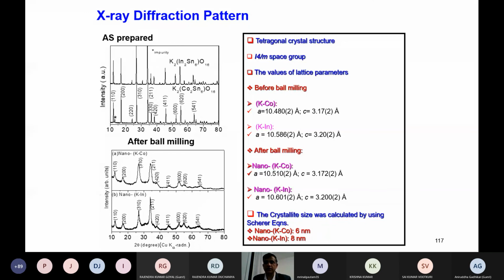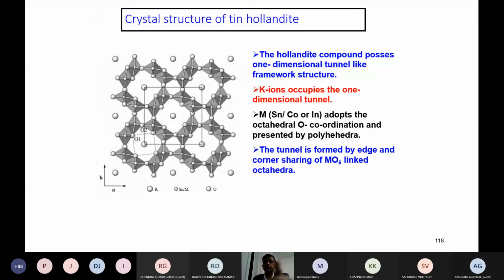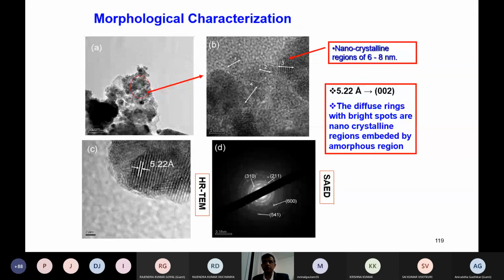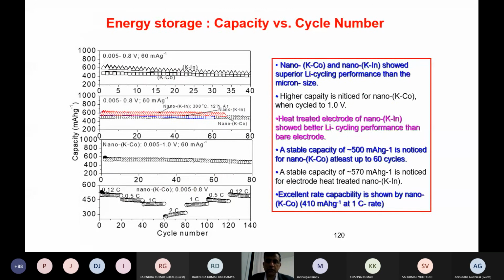And these are the various parameters, like the tetragonal lattice parameter, etc. These are the hollandite-type tunnel structures, which is very important for lithium diffusion, etc. Anyway, we can check with TEM, so it is complementary. You can see your materials are nano size.